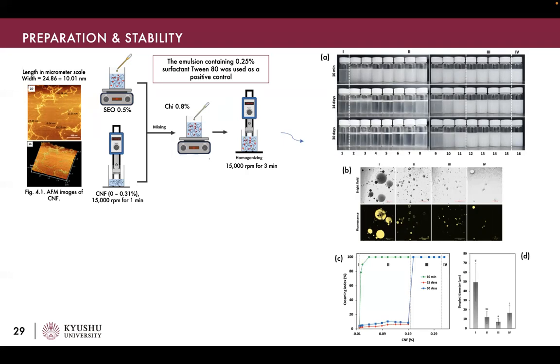As in this figure, a preliminary test was performed to select the optimum dosage of cellulose. It was divided into 4 groups. The first group exhibited a creaming index of the emulsion in the absence of cellulose.